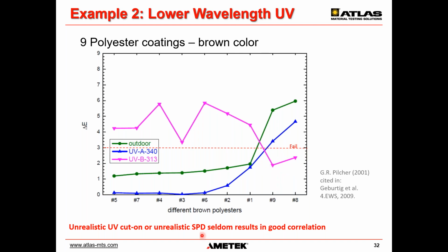Also coatings number 4 and 6, which were very good performers outdoors. Here you see, outdoors good performers. They are ranked being the worst in the UVB 313 test. I think that should do it. For UV fluorescent, I think you get my point. Don't use UVB 313 tests if you don't very well know what you are doing. For certain tests that may work well, but you need to know what you are doing.